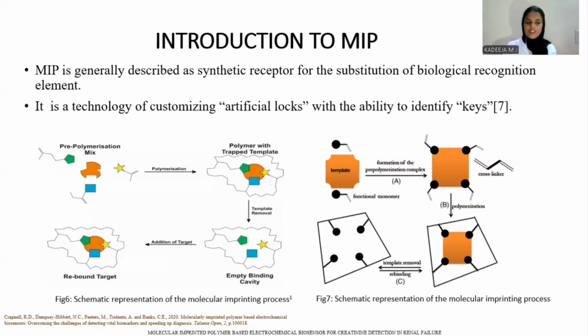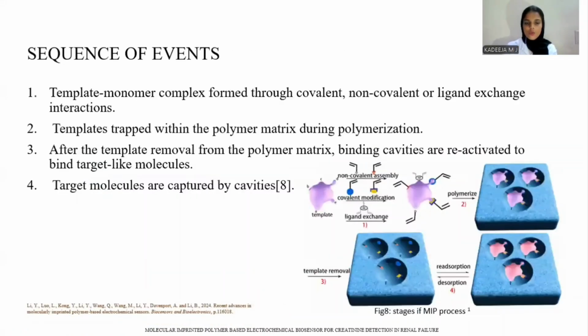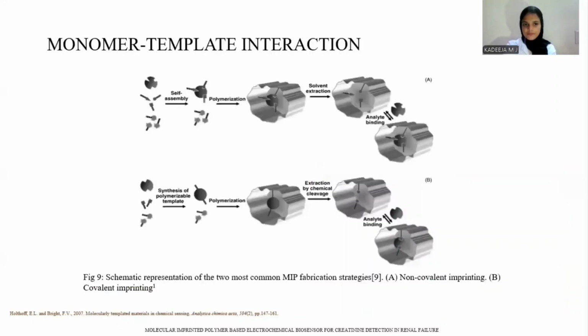So from the figure itself, we can get an idea of what is happening here. There's a template, and only the particular polymer can be trapped in that template. The sequence of events: first, the template-monomer complex is formed through covalent, non-covalent, or ligand exchange interactions. The template is trapped within the polymer matrix during polymerization. After the template is removed from the polymer matrix, these binding cavities are reactivated with the target molecule. In our case, our target molecule is creatinine. So after the template removal, the cavity is filled with creatinine, our target. The target molecules are captured by the cavity.